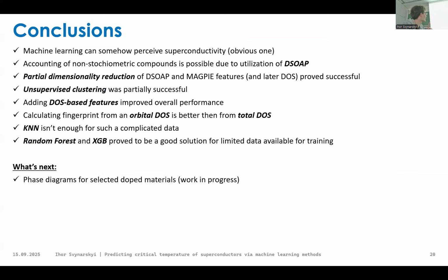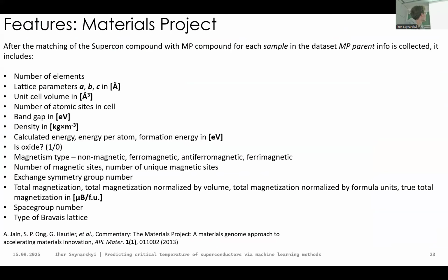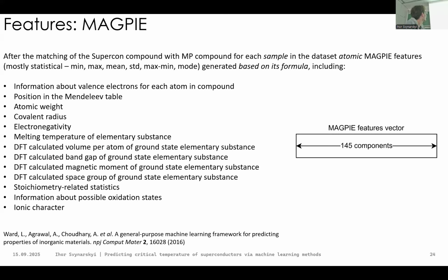Maybe I have an additional slide. So, features taken from the material: in this MAGPIE descriptor, we had some statistical information about atomic weights, covalent values, even atomic number. It looks at the formula, saying we have iron and oxygen, like 10 oxygens and 5 iron atoms, and then we calculate the average atomic weight, the minimal, maximum, and standard deviation. So it's accounted for in some form.